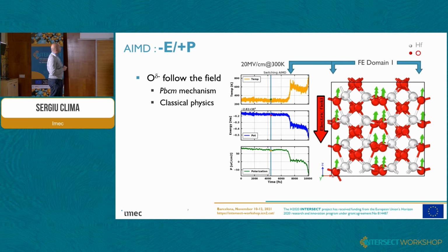The polarization will go from up to 0 and then to polarization down when we have the electric field applied anti-aligned to the polarization itself. So this is what I would call classical ferroelectric switching. We put an anti-aligned electric field to the polarization, and we have the two domains switching, one and then the second one.